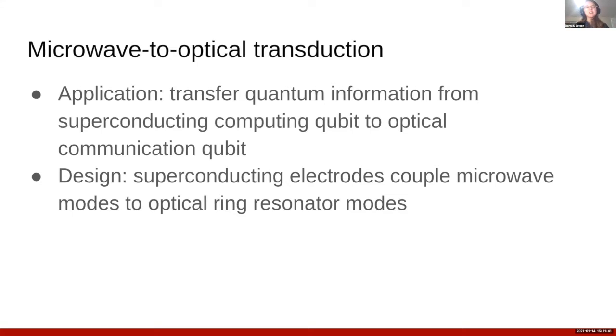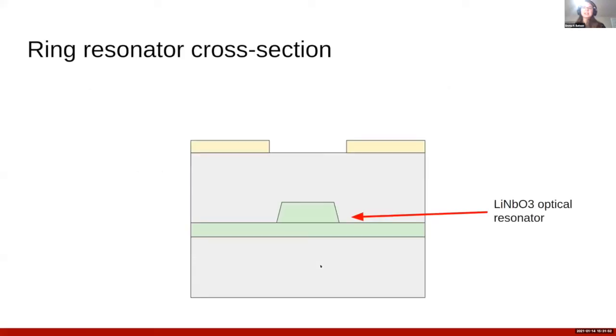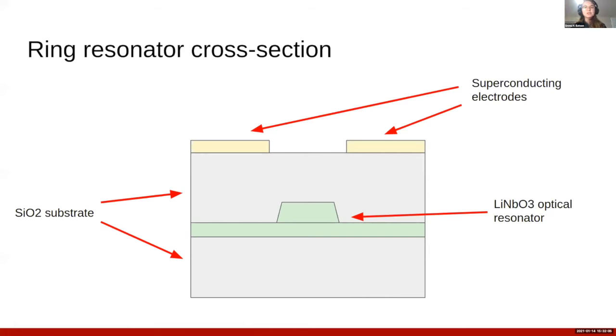They've got this design where you use superconducting electrodes to couple these microwave modes to the optical modes in a ring resonator. Here's a cross section of what that might look like. So in the middle here, we have our lithium niobate optical resonator surrounded by the silicon dioxide substrate. And sitting on top of all of that, we have these superconducting electrodes.